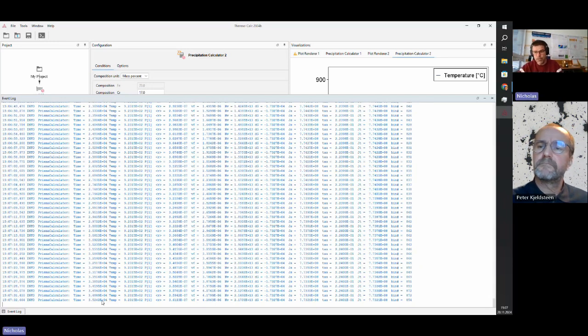And what people do typically is they have certain experiments, right? They did trial runs with similar materials, with similar processes, and then they try and change all these parameters, like the mobility enhancement factor, like interfacial energy. They try and modify those to fit with their experiments, right?